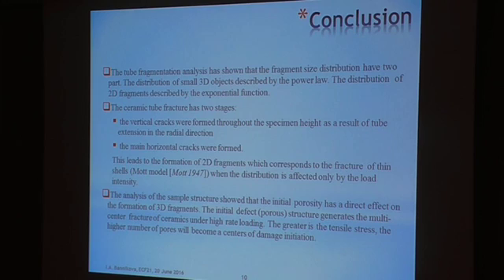The analysis of the sample structure shows that the initial porosity has a direct effect on the formation of three-dimensional fragments. The initial defect structure generates the multicenter fracture of ceramics under high rate loading. The greater the tensile stress, the higher the number of pores will become a center of damage initiation. Thanks.